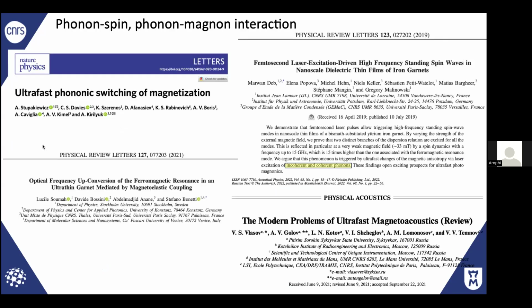From the physics point of view, as I mentioned, phonon-spin and phonon-magnon interaction is something very interesting as well, because you can modulate, let's say, the magnetocrystalline anisotropy in a system. You can, of course, play with the exchange interaction by moving atoms as well. And if you pump phonons specifically, you can induce some switching of the magnetization. This is quite a recent paper. So there are different situations where phonons can be used to drive magnetic properties, so magnons in different situations. There is a recent review about what we call magneto-acoustics.